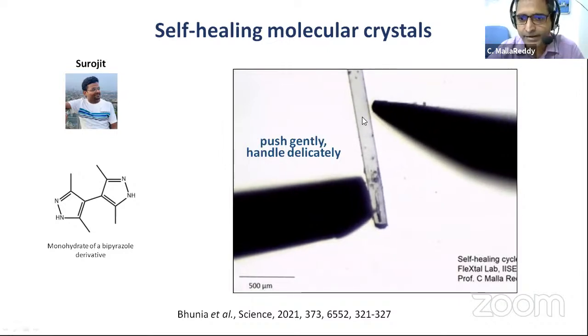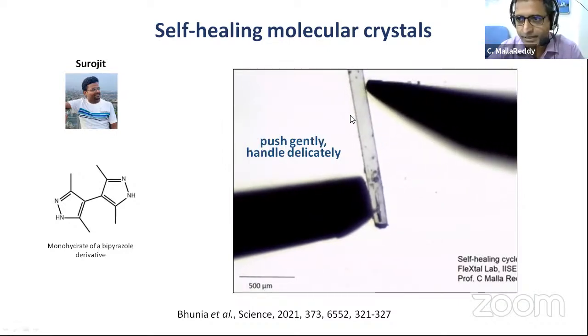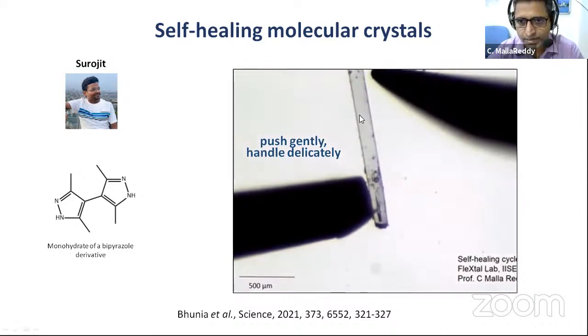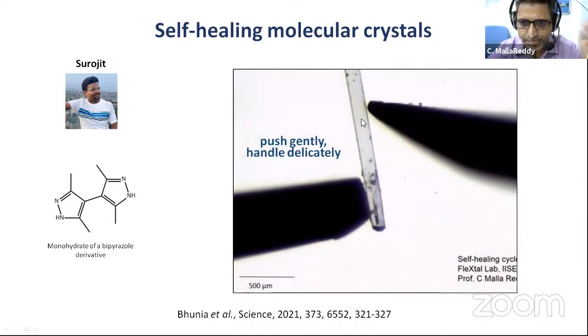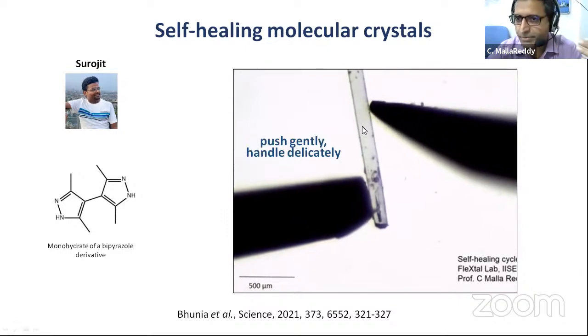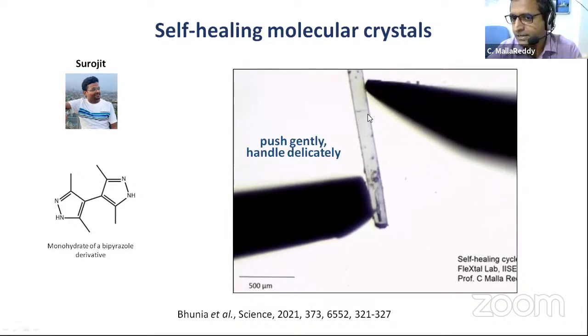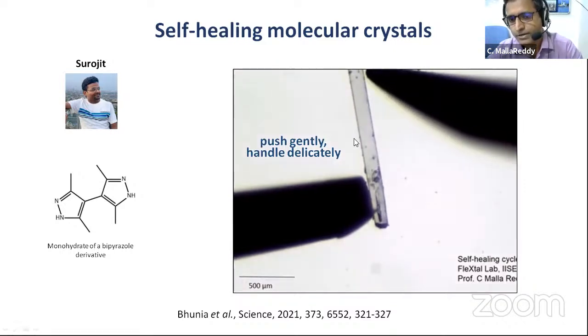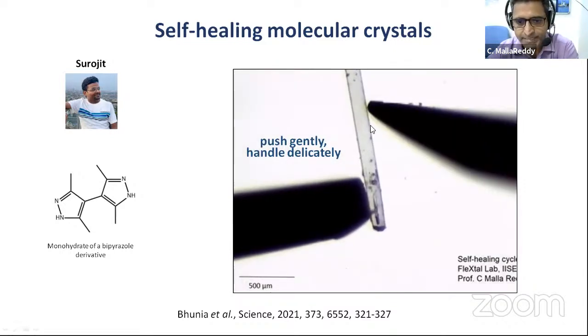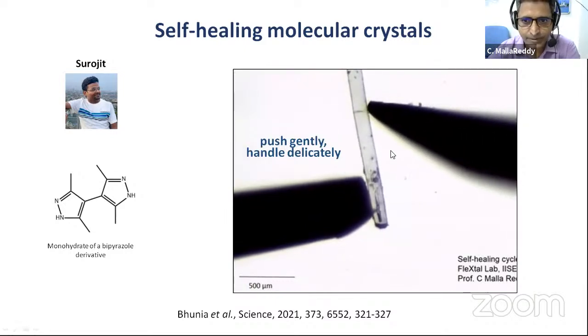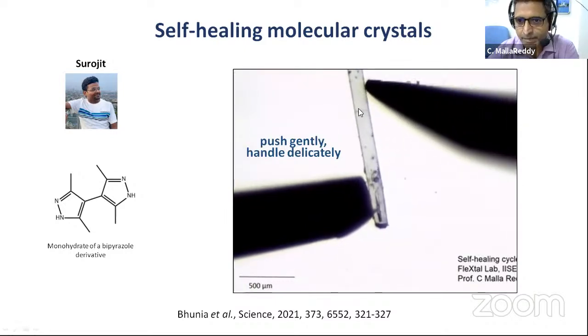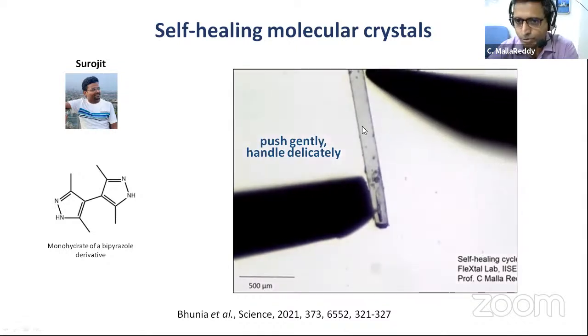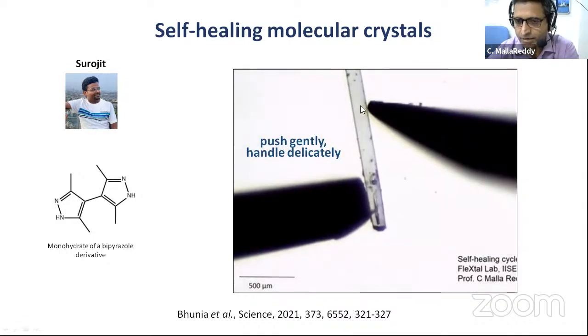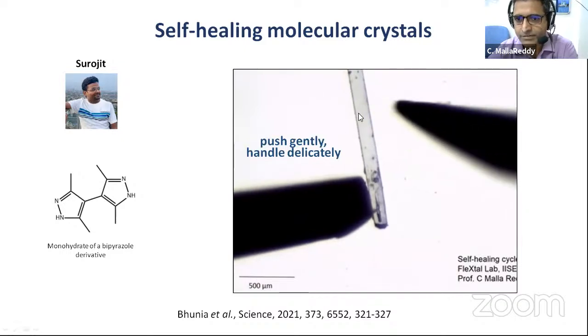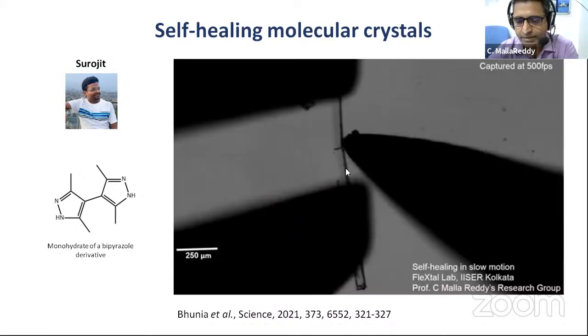And once you make a crack, you don't expect 100% healing, even in other materials as well. Of course, there are some other materials with different mechanisms where the crack region becomes much harder. But here in this case, it is not 100% healing, as it suggests. So wherever you push it, it cracks exactly at the same place, because that is a weak point. But the most important thing is it comes together on its own. You don't have to push it to put it together. And when it heals, it actually heals perfectly. Even after there is a visible crack, they still hold together, and then they nicely sit together.